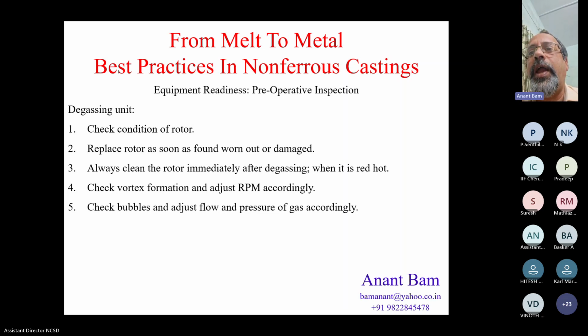Check the vortex formation and adjust RPM accordingly. You have to ensure that a clean vortex is formed. The vortex should be visible. And a thumb rule is that whenever the vortex is formed, the eye of the vortex goes to a depression and on the side walls, the metal rises a little bit. The level difference between the sidewall and the eye of the vortex should be approximately 4 inches or 100 mm. That's a thumb rule for formation of a good vortex. You have to adjust the RPM of the rotor till you get such a good vortex formed in the crucible.